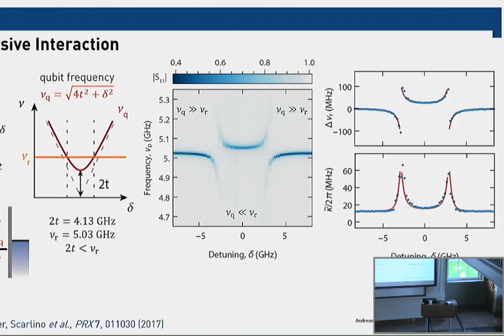And you can already from the frequency shifts do a master equation simulation, using the line width of both the cavity and the quantum dot to analyze the cavity QED parameters of the system, which include the coupling strength g, the energy relaxation rate of the quantum dot, the dephasing rate of the quantum dot, and the line width of the cavity. And this is mostly from this dispersive data. Here you would already see the coupling strength is larger than any of these decoherence rates, and therefore this should go into the strong coupling limit.